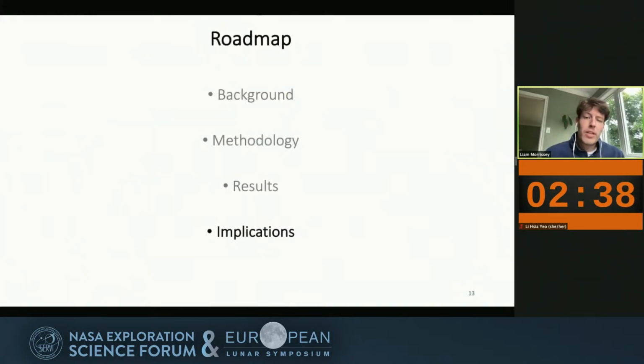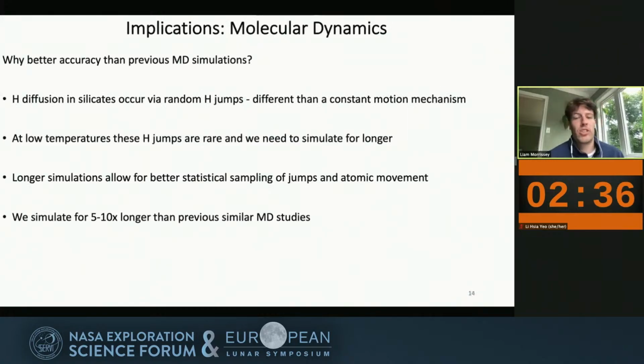So I can basically wrap up here with a couple of the implications of our findings. First, from an MD point of view, we showed that H diffusion in silicates occurs via random H jumps, and this is very different from a constant motion mechanism. Therefore, at low temperatures, these jumps are rare, and we need to simulate for longer. Longer simulations allow for better statistical sampling of jumps and the atomic movement. And as we noted, we simulate 5 to 10 times longer than previous similar studies.